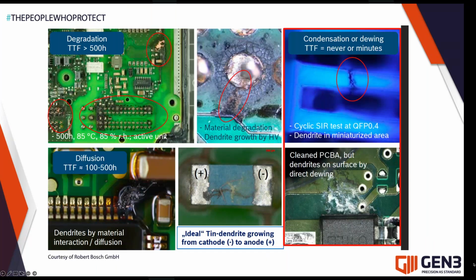So again, an image from Robert Bosch. So here we can see failures developing in this zone at the bottom of the picture, and this is after 500 hours. So these failures don't always happen instantaneously. Typically, they need at least a week, but they can be weeks and weeks. And so 500 hours is typically about a month's worth of testing at the 85/85 conditions. So you sometimes have to wait some while before you'll see this failure mechanism.